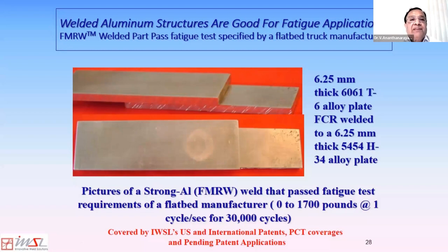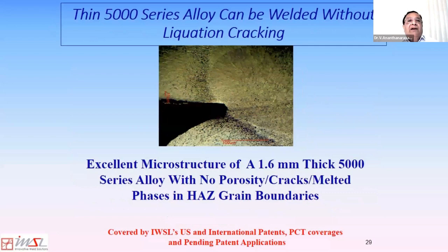So with this method of welding, it is definitely possible to weld thick-thin aluminum metals, heat-treated aluminum alloys with high structural strength for fatigue loading. And when you cool the heat-affected zone using water-cooled copper alloy electrodes, you see that the second phases in the heat-affected zone do not melt and crack anymore because they are kept cooler by the water-cooled copper alloy electrode.